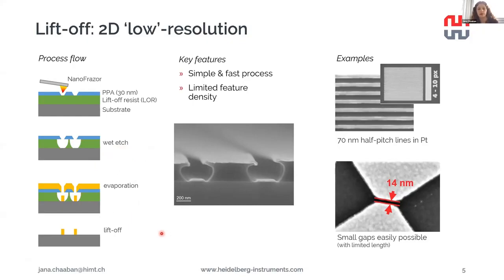And in doing so, we can reproducibly achieve patterns that are about 100 nanometer in size. And we can also, depending on design, achieve smaller feature sizes as well. But in this case, the feature density is limited. So if we were to transfer higher resolution and also more complex or arbitrary shapes, we need to modify this resist stack a little bit.